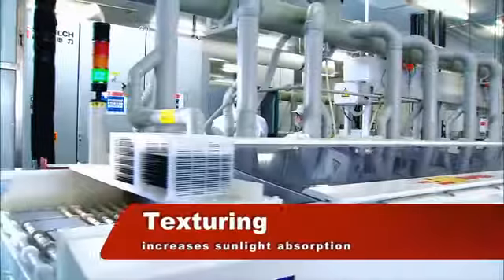Cell production begins with Suntech's patented texturing process. An etching solution forms pyramid-like structures on the surface of the monocrystalline silicon wafer, reducing reflectivity from over 30% to around 11%.